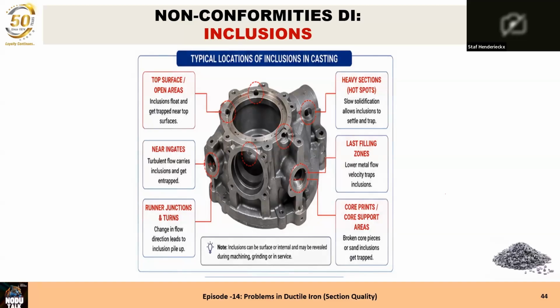And many times it's around core prints and cores which have a different section thickness, a very thick section to a thin section. Then it can be that it breaks there or the coating is not proper and the liquid metal will break out core pieces and it will be sent into the casting itself.